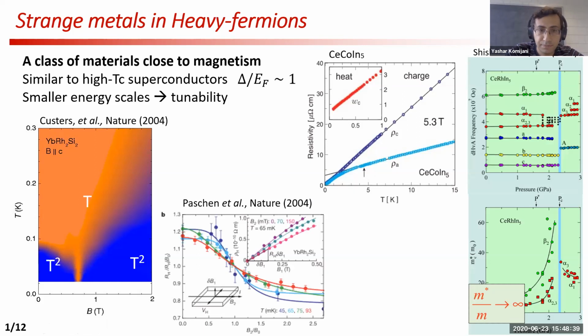systems. For example, here you see the Hall measurements by Silke Paschen on this YbRh2Si2, where around this critical magnetic field, the Hall constant jumps and it becomes sharper at low temperatures. And these are famous measurements by Shishido and co-workers on cerium rhodium indium 5, where the magnetic oscillations show a jump at the critical pressure, meaning that the Fermi surface has changed. They can also extract the effective mass of carriers from the amplitude of the oscillations, and this is shown here, which shows that the effective mass diverges, signaling some sort of a localization.